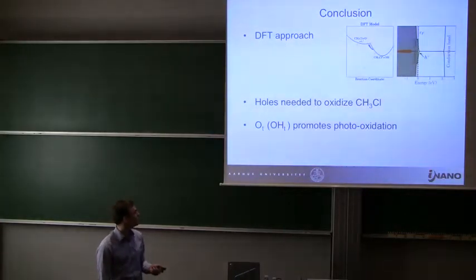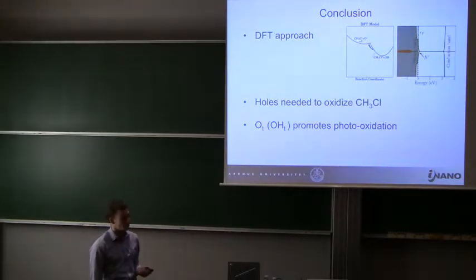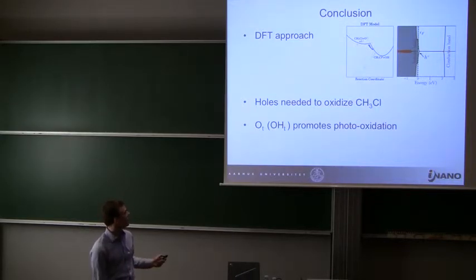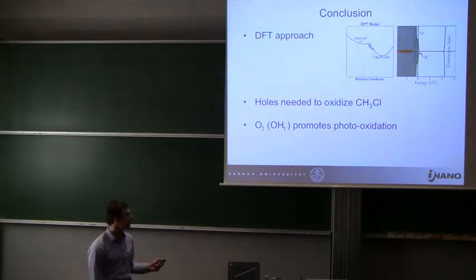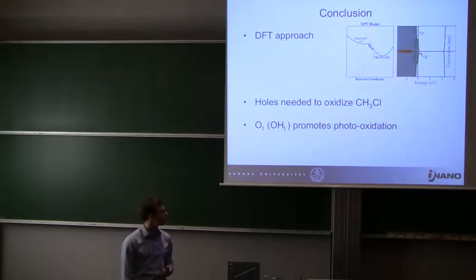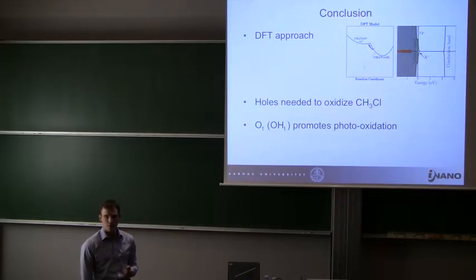So just to conclude, I tried to show you that we had a DFT approach within which we could try and model these photoreactions. This gives some, maybe not convincing results, but it is something that we seem to be able to believe in. We saw that the holes were needed for the oxidation of methyl chloride, and that terminal oxygen and to some degree terminal hydroxyl ions promote the photooxidation of methyl chloride. Thank you for your attention.